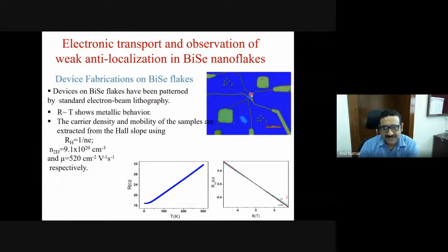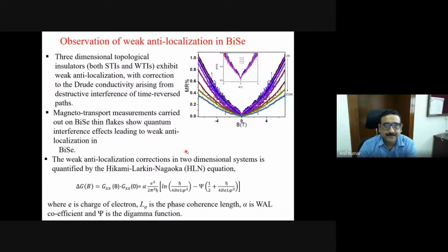But here, unfortunately, the entire region is conducting. This tells me that there is more self-doping in the bulk, and the bulk is also conducting. So that's why the carrier concentration is a bit high here. And we then measure magnetoresistance as a function of applied magnetic field.